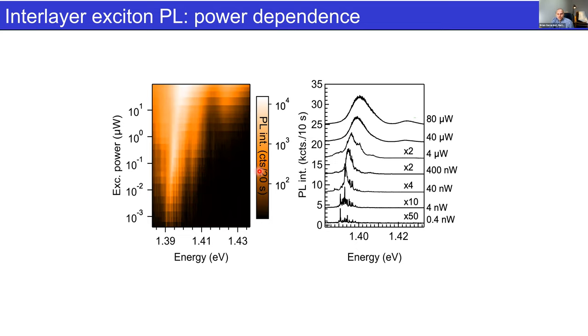Here I show a simple power dependence. At extraordinarily low power, less than a nanowatt of excitation, we see the sharp peaks. As we start increasing the excitation power, we have a clear transition from these sharp isolated spectral peaks: they merge together, and they start to blue shift at a certain point. Then at high excitation powers, we observe another peak arise. The line width of what I would call an ensemble interlayer emission peak corresponds to about 5 meV, on par with the best reports out there. So it's a clean material.